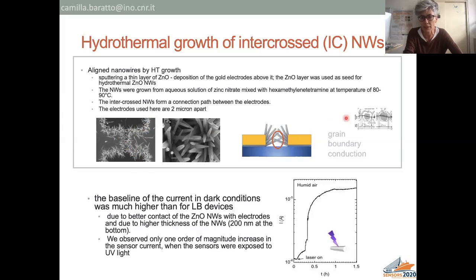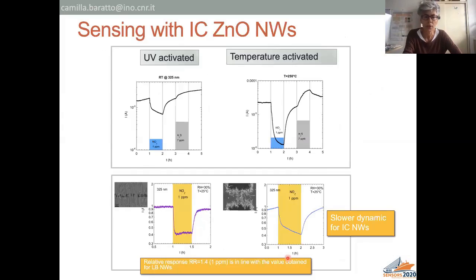In this case, the conduction is more a grain boundary conduction, like in the polycrystalline sample. And the baseline in this case is much higher than in the case of nanowires aligned by Langmuir-Blodgett, and the effect of UV light is less, because we have only 1 order of magnitude increase.